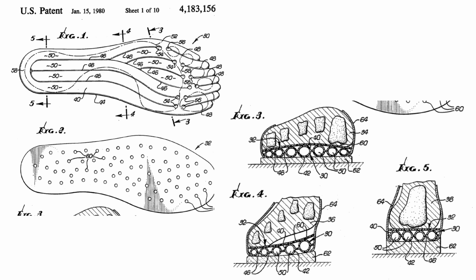gas which will not diffuse appreciably through the walls of the insole material for an extended period of time, e.g., several years. The two most desirable gases have been found to be hexafluoroethane, e.g., Freon F116, and sulfur hexafluoride. Other gases which have been found to be acceptable, although not as good as hexafluoroethane and sulfur hexafluoride, are as follows: perfluoropropane, perfluorobutane, perfluoropentane, perfluorohexane, perfluoroheptane,